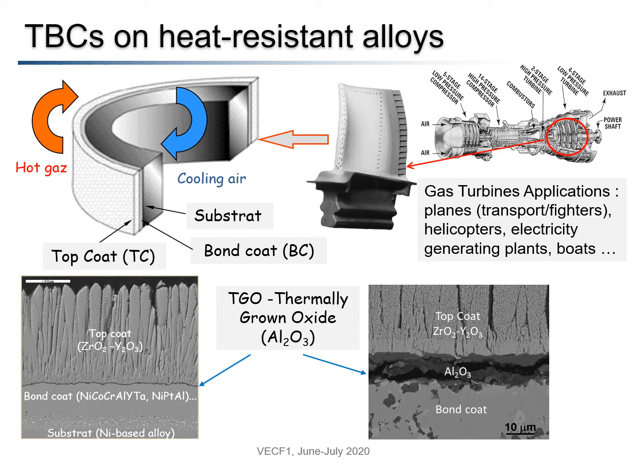TBC, thermal barrier coating system, on nickel-based superalloys is typically composed of three layers. The aluminum containing corrosion-resistant metallic bond coat, the thermally insulated ceramic top coat, and the thermally grown oxide, TGO, predominantly alpha alumina. This layer forms during high temperature exposure under service conditions due to oxygen diffusion through the top coat and oxidation of aluminium present in the bond coat.